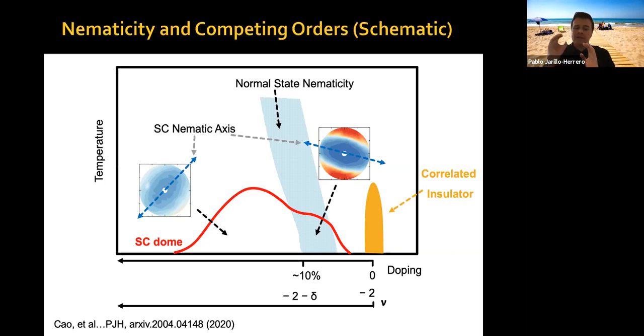Now, this is something that can be caused by various different things. In particular, it can be caused by order parameters which are known as non-S wave. You can have nematicity due to P wave order parameters, due to D wave order parameters, due to various types of order parameters. What I would say is that seeing nematicity in the superconducting state, at least theoretically, is a strong indication that there is a non-S wave order parameter, and a purely S wave order parameter doesn't give you an anisotropy of your superconducting state properties with things like parallel magnetic field. So nematicity is an indication that you may have a non-S wave order parameter.